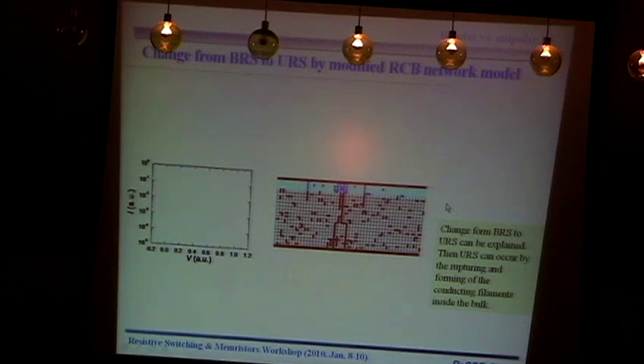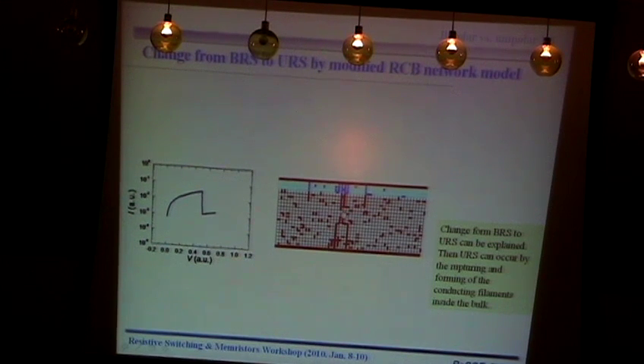Now, let's move on how this bipolar switching can be changed into unipolar switching. That's important because suppose you have this kind of a network, then the percolating network. But suppose some of the state attached to this percolation network in this interfacial region has the very, very highly conducting region like this. Then what will happen will be, because it has a very high conductivity, maybe the breakdown of this, the insulating layer that occurs in this region. So it will enter to the unipolar.